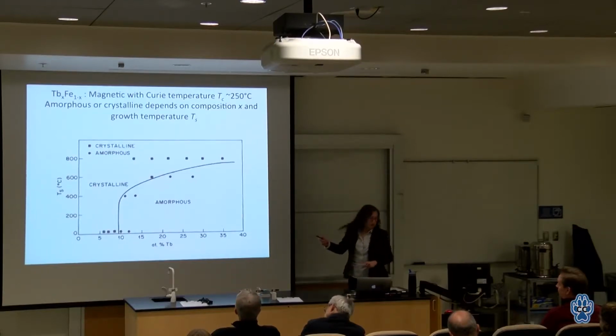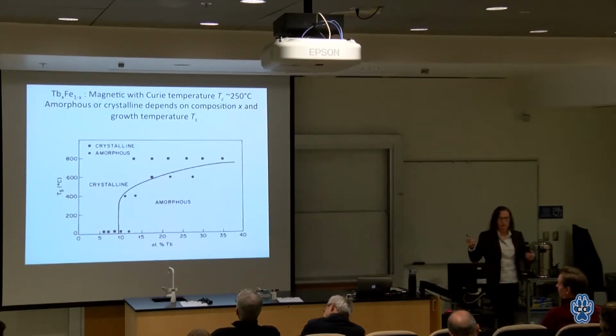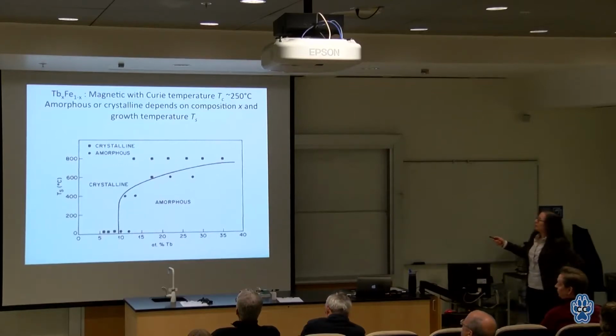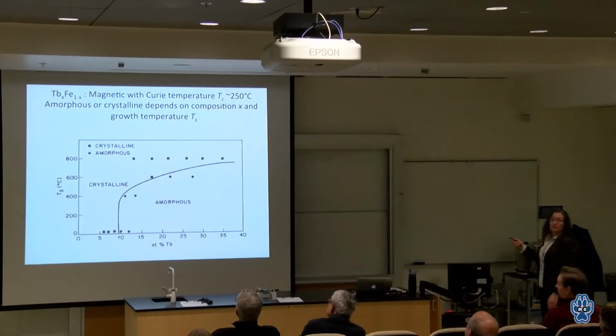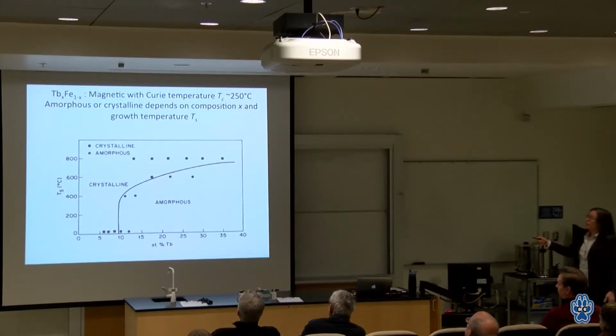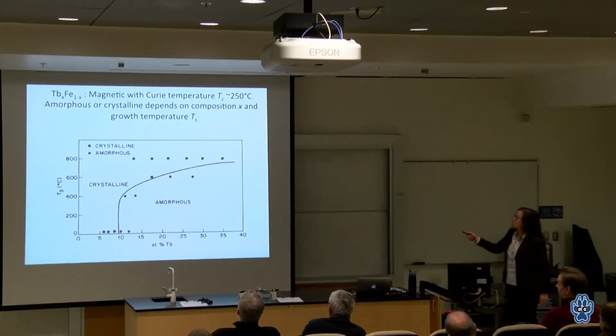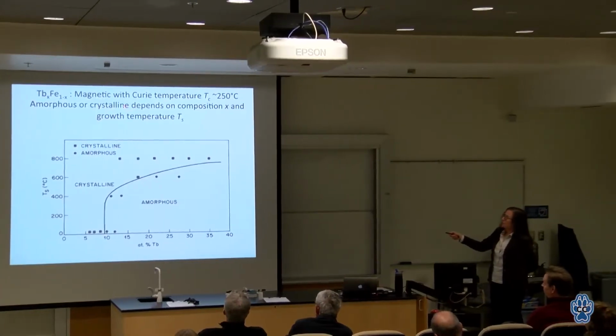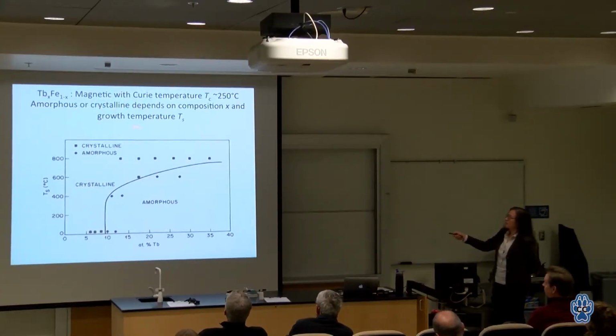So I'm now going to turn to my first non-silicon example. I'm going to run through a few examples and then come back at the end to silicon. So this is an alloy of terbium with iron. And so it's magnetic. It's actually a pretty good magnet. It has a Curie temperature well above room temperature. It can be made either amorphous or crystalline, depending on composition, depending on growth temperature.